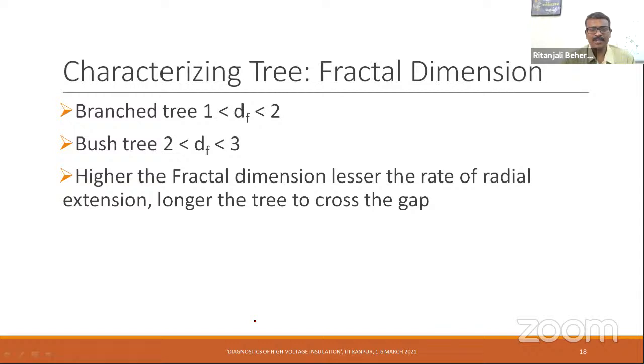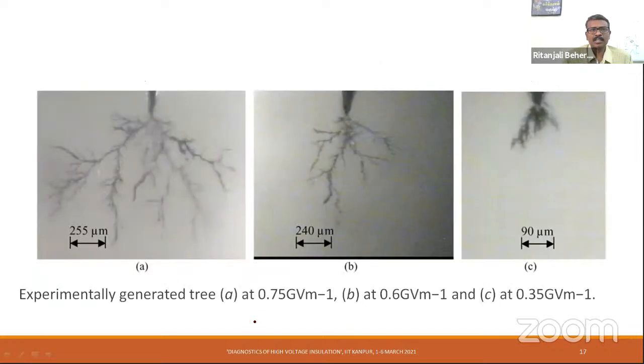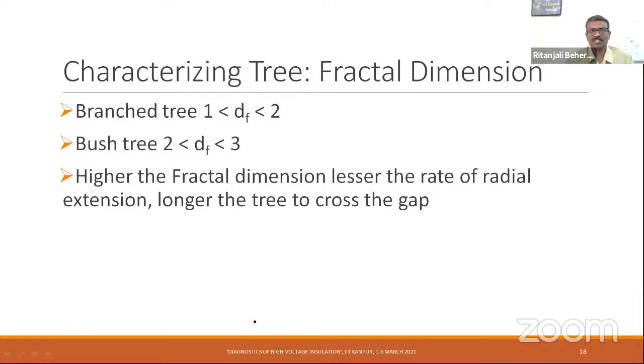How we can characterize a tree is by the fractal dimension. We have several methods to find the fractal dimension of the tree. It is primarily characterizing the volume of the tree branches, or the area of the tree branches, we can call it. So that is what a fractal dimension is. For a branch tree, it will be between 1 and 2. For a bush tree, it will be between 2 and 3. So the higher the fractal dimension, the lesser the rate of radial extension, which means it will be more and more bushy. From a bushy tree, the branches would not develop that quickly. So the higher the fractal dimension, the lesser the rate of radial extension, and the longer the tree takes to cross the gap.